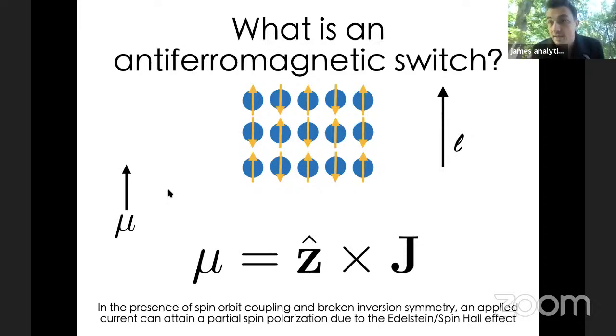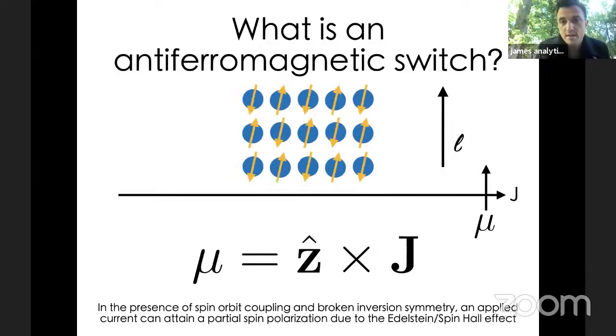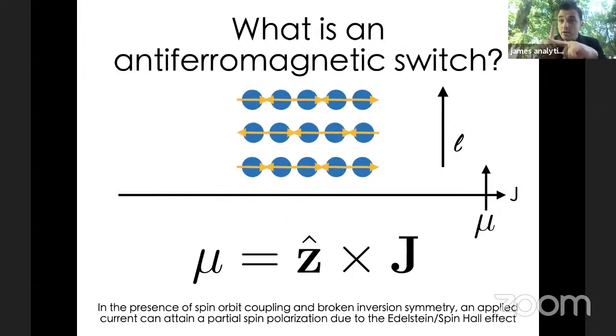Then when you apply an electrical current, you end up getting, due to the spin orbit coupling, and perhaps there's a strong Rashba term in the system, the broken inversion symmetry in the system, given by this polar vector Z, allows you to have an electrical current that's very slightly spin polarized. And because it's slightly spin polarized, you can impart an angular momentum onto the antiferromagnet itself. The result is that you can rotate the Néel vector from one direction to the other. And that's what we mean by the switch. It's not that you're turning this antiferromagnetic order on and off, you're rotating the antiferromagnetic order from being oriented in one direction to being oriented in a perpendicular direction.